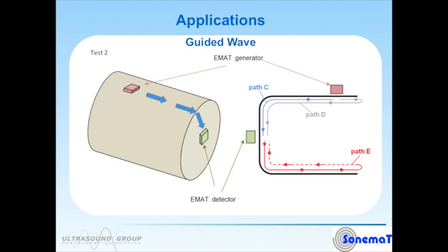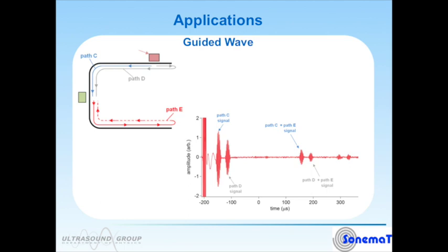What's surprising, looking at the A scan, the time domain waveform on the bottom right hand side here, is that the signals travel around these features of this can with relatively little loss. There is very little reflection when an SH guided wave goes around a very sharp corner. However, if there's a defect there, it will reflect a significant amount of the energy.